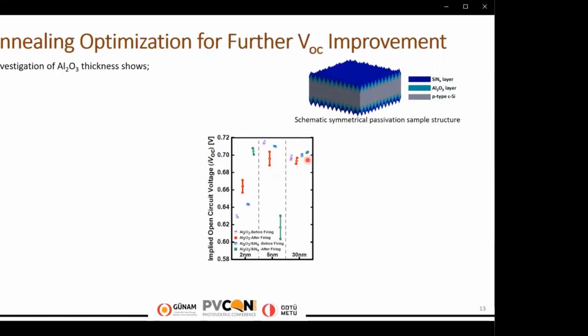And implied VOC improves after firing the 2 nanometer aluminum oxide silicon nitride stack. And this improvement is because hydrogen diffusion from silicon nitride to the silicon aluminum oxide interface is more feasible through the 2 nanometer layer, improving chemical passivation.